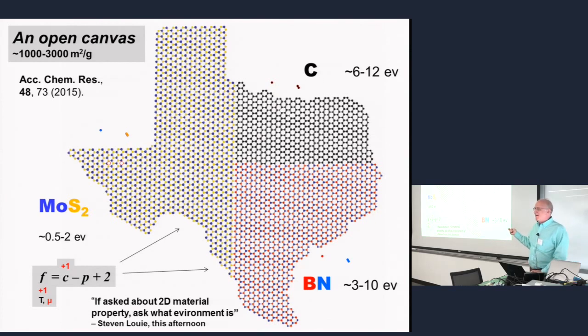Anyway. So we now will talk about this intentionally hybrid, and now my colleague experimentalists, magically, they really produce this type of hybrids. In this case, it's just an illustration. This is some molybdenum disulfide, this is graphene, this is boron nitride, and you can stitch them together with that level and this level of perfection of the interface, which I will talk about later. But basically, they do exist.